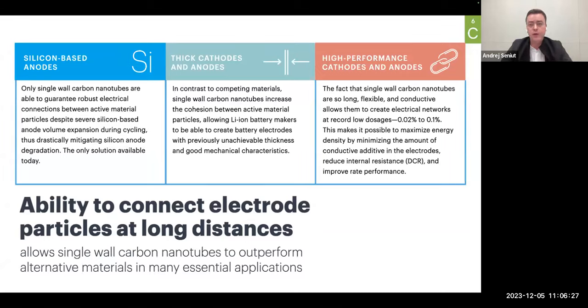One of the applications, and perhaps if you're familiar with our product, you know really well, is silicon-based anodes. This is a system with very high volume expansion and contraction. And here, these long and flexible single wall carbon nanotubes, which are able to establish reliable connections between silicon anode particles, are very useful. The second application, which we found out recently, is thicker electrodes. And the mechanism of the work is actually the same.